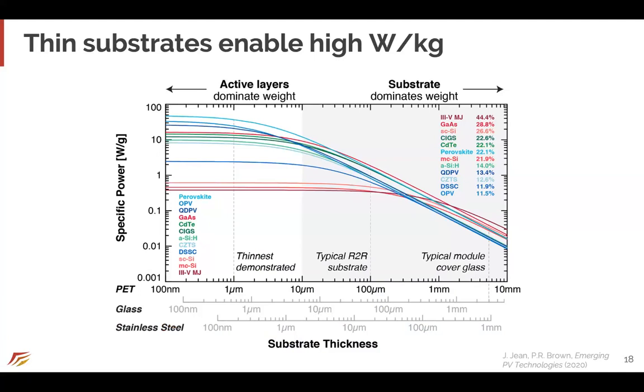This is showing the specific power in watts per gram against the thickness of different substrates, on a log-log scale. Obviously these efficiencies are a bit dated, but linear changes don't really matter on a log scale. At the thick substrates, the substrates dominate the weight of the full module or cell. In contrast, as you go to the left to a regime with very thin substrates, you get to a point in the limit where active layers dominate the weight. In reality, you're going to be somewhere in between. But it's only on this left side, where the active layers start to dominate, that having lightweight, thin, flexible active layers really matters. So perovskites start to shine when you go to thinner substrates, alongside other emerging PV technologies.